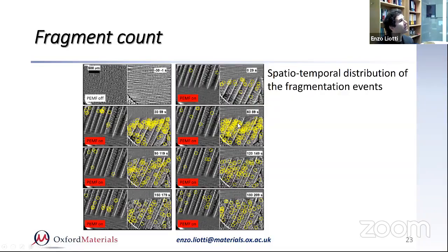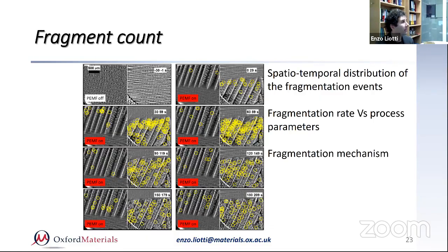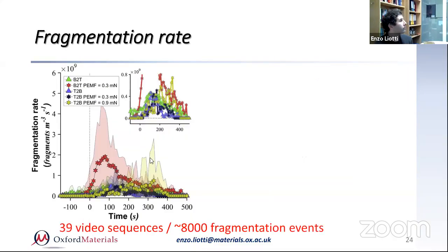breaking events is the information we could learn about this, and the fragmentation rate against the processing parameter. And what we were trying to achieve and to understand is the fragmentation mechanism. So by analyzing 39 video sequences and counting pretty much 8,000 fragmentation events, we were able to produce this curve. This curve is the basic fragmentation rate curve as a function of time for the various cases.